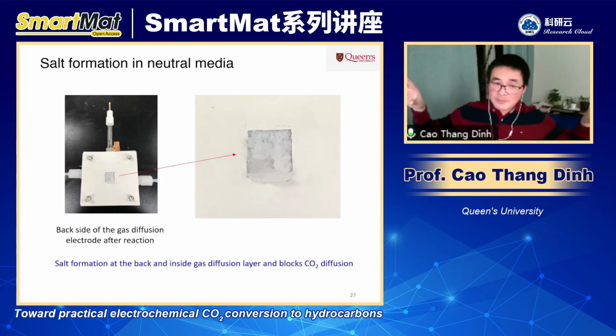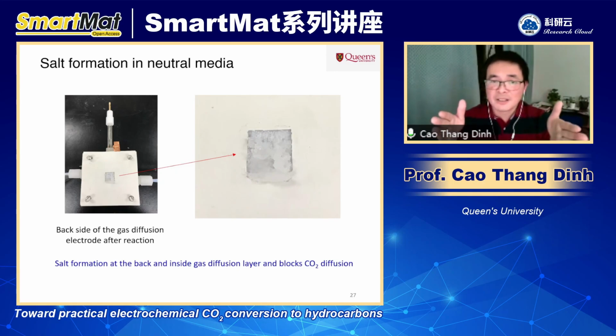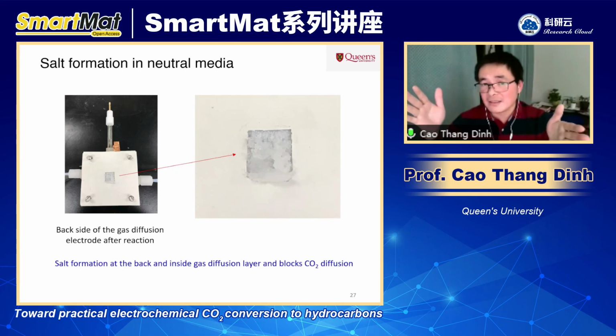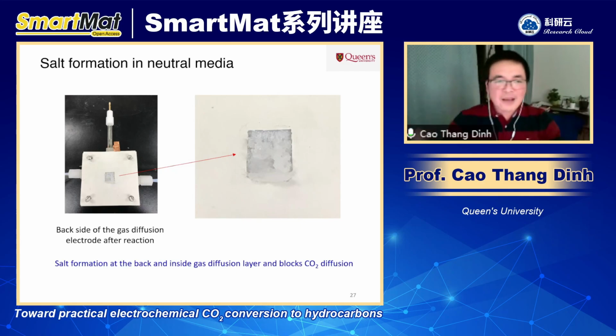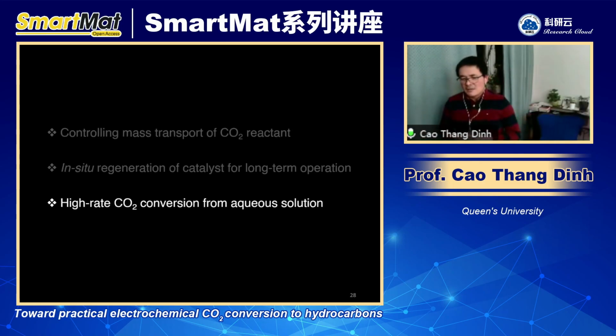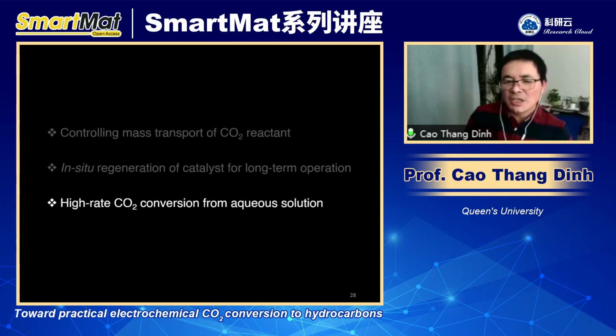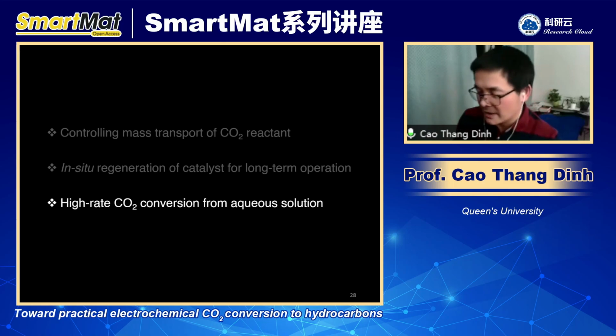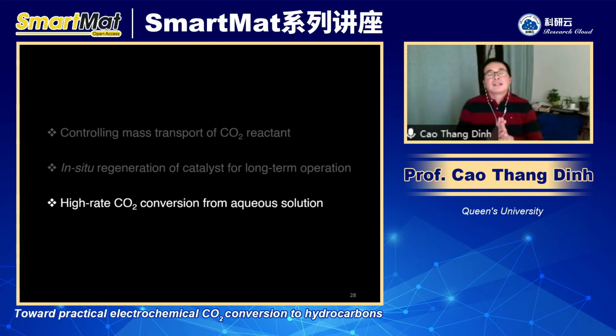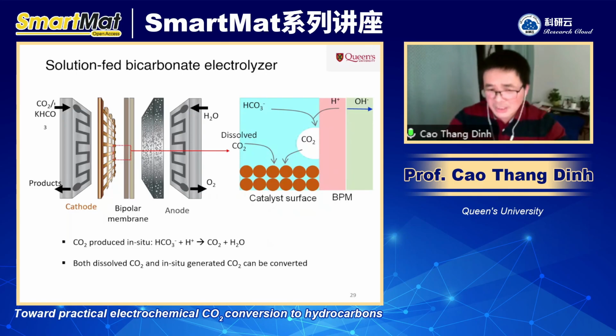So there are three different problems, but two problems are linked to the gas diffusion layer, and one problem is linked to the catalyst layer. So you may ask, can we do CO2 conversion at high reaction rate, but without the gas diffusion layer? Can we stop using the gas diffusion layer in CO2 conversion? And that is the last topic of my talk today. I'm going to talk about how we can achieve high rate CO2 conversion, which is at high current density, but using the CO2 in the aqueous phase. It's not the gas phase. We do not use the gas diffusion layer.